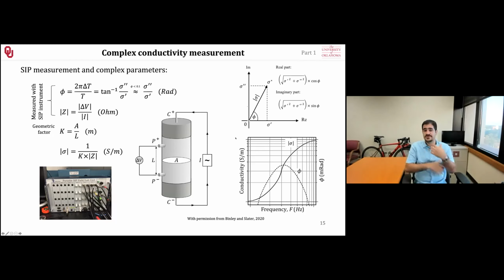And then we can use these different measures for different applications. So as you remember, the imaginary part represented the energy storage or the polarization. It depends on the surface area, on the pore size distribution, and so on. And the real conductivity depended on the saturation, porosity, and the salinity. So we get different properties from the subsurface or our sample with this complex conductivity method.